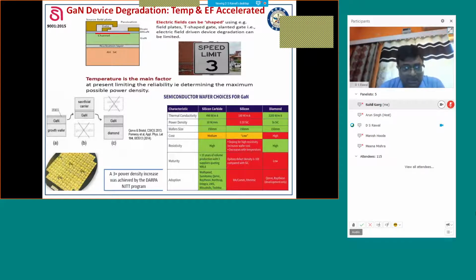So what is normally done is, once the device is completely fabricated on silicon carbide substrate, the complete wafer is mounted on a carrier sacrificial wafer, and then silicon carbide is removed completely, and the thinned wafer is mounted on a diamond substrate, because diamond has the highest thermal conductivity, almost 4 times that of silicon carbide, and then this sacrificial carrier is removed. By this way, the device performance has been reported to be enhanced by almost 3 times, and a lot of work is going on.